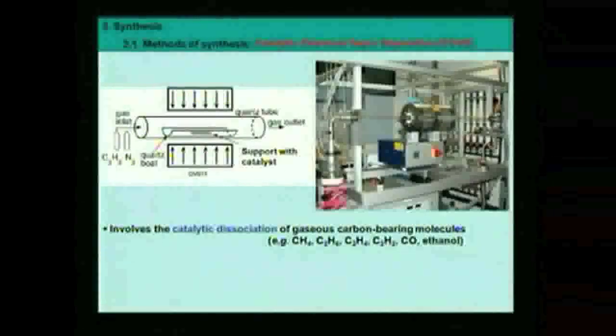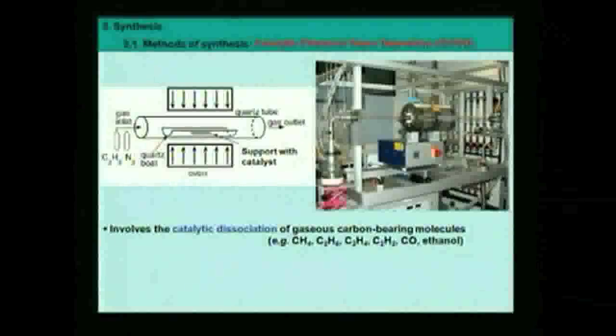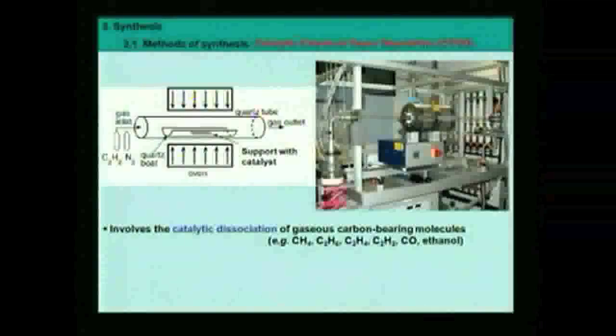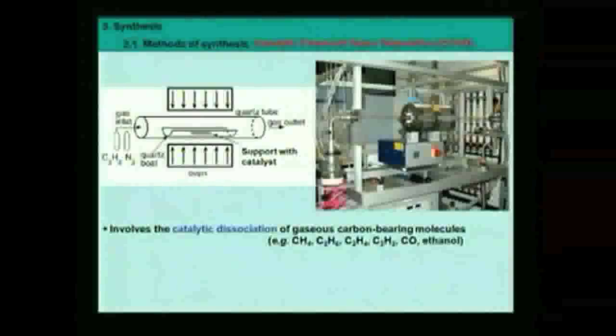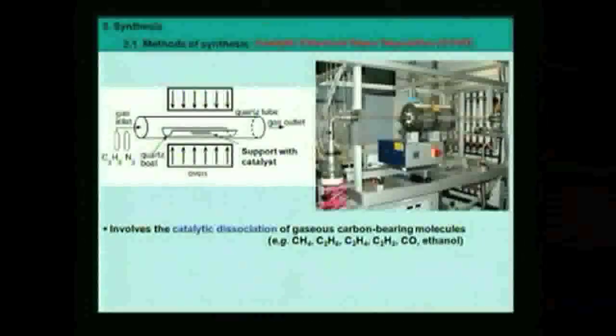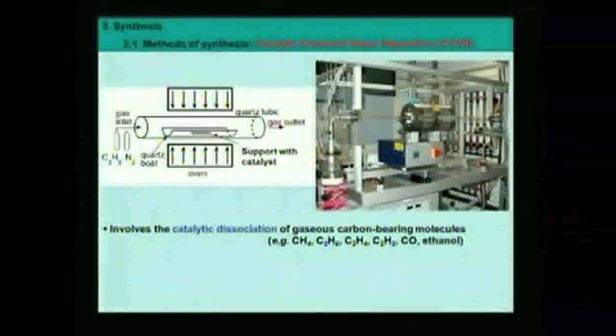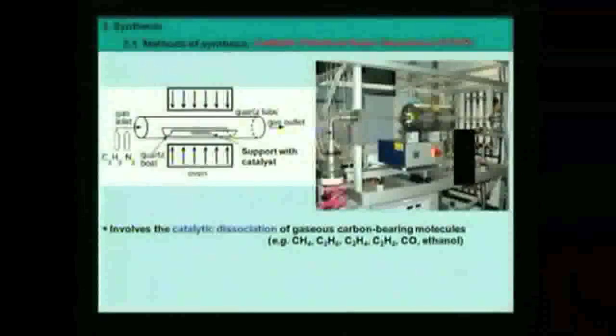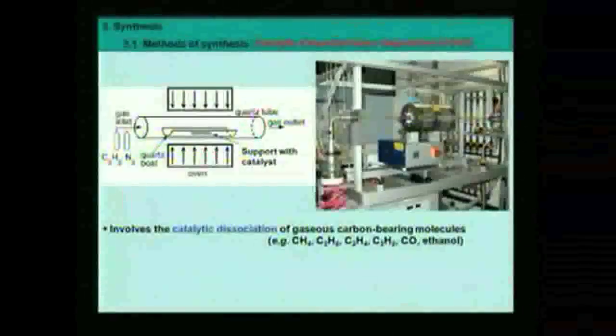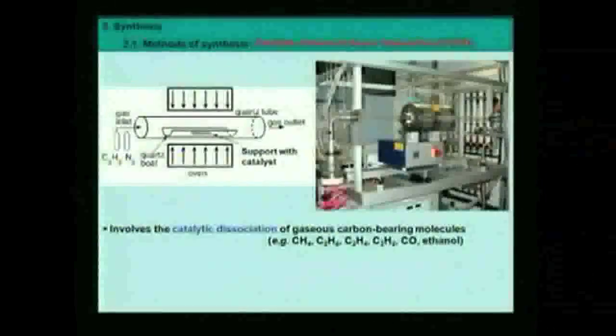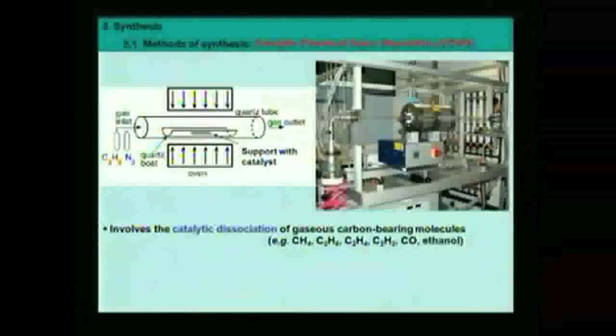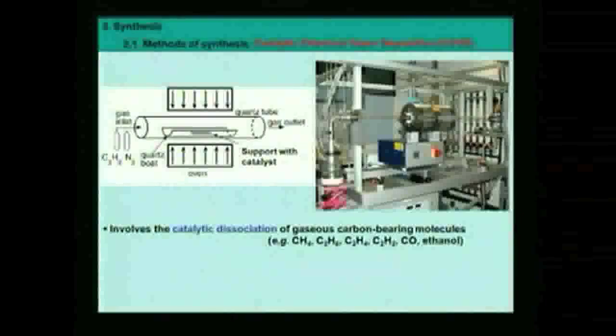How is it like? So actually you see here a picture of a CCVD reactor. You've got a furnace, usually a tubular one, with a quartz tube acting as a reactor, passing through the tubular furnace. You can see the long quartz tube here. Inside the quartz tube is put a catalyst, usually deposited on a support, inside a vessel, a boat, inside the reactor. This is heated by the furnace, the oven, and then to grow carbon nanostructures, we will introduce carbon containing gases, like here acetylene, but you can use many other types of carbon bearing molecules as carbon precursor, like methane, ethane, ethylene, acetylene, carbon monoxide, ethanol, benzene. Many types of carbon precursors can be used.